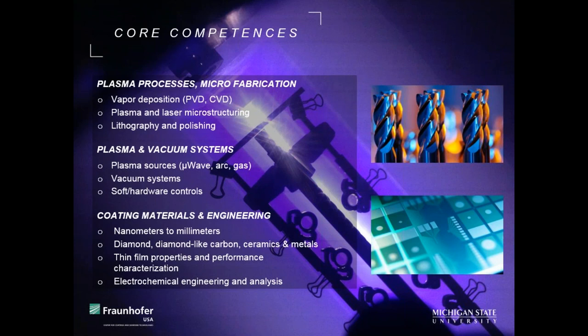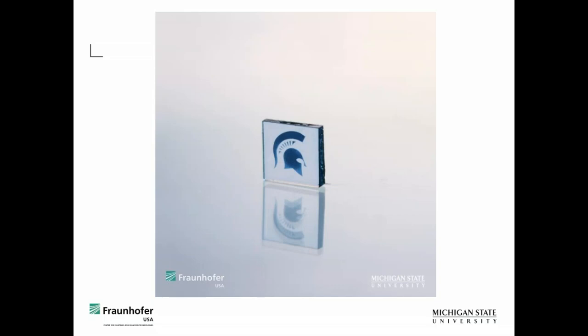And there are some pretty robust capabilities with respect to microfabrication, especially microfabrication of diamond. So here is one of the interesting single crystal diamonds. If you ask my colleagues if we're growing diamonds for gemstones, it makes their blood boil. But one of our largest competitors was recently bought by De Beers, so they're going to switch to doing laboratory grown diamonds. You can actually grow them with higher purity than what you can get out of the earth. So that's worth considering. But nonetheless, we've had a few one-off type projects from, like, the MSU Foundation.